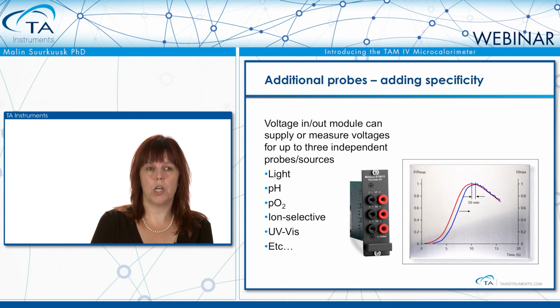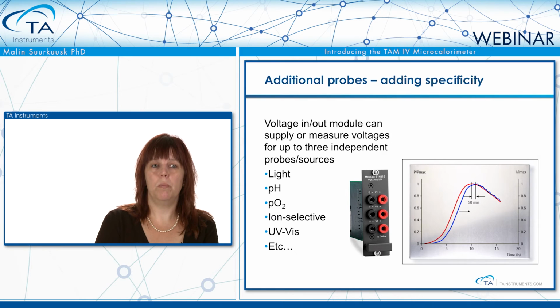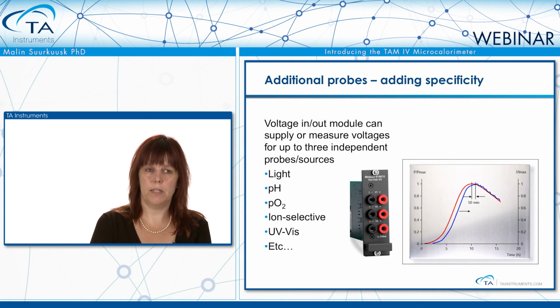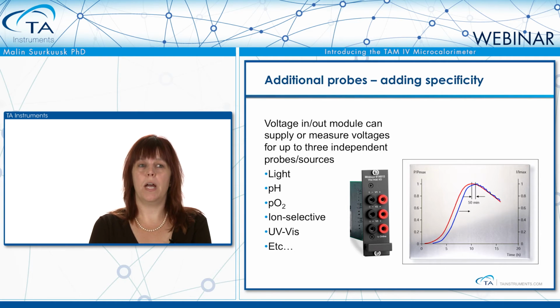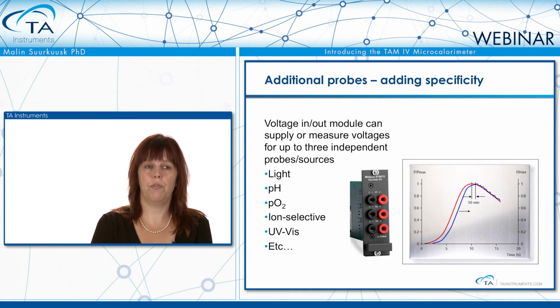The example shows simultaneous measurement of heat flow and chemiluminescence of a polymer that is oxidizing. Chemiluminescence will only measure the light emitting step in an oxidation reaction, while the heat flow or the calorimeter will measure all the reactions that go on. This is why we have a little shift of 30 minutes of the curves. But it's essentially the same reaction, just that it's different parts of the reaction we are studying here.